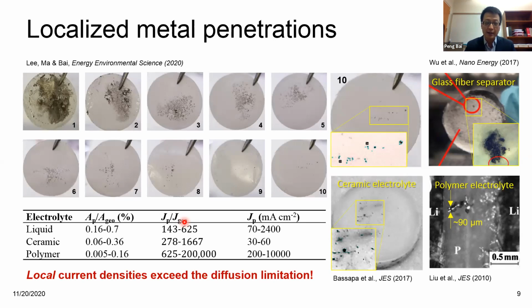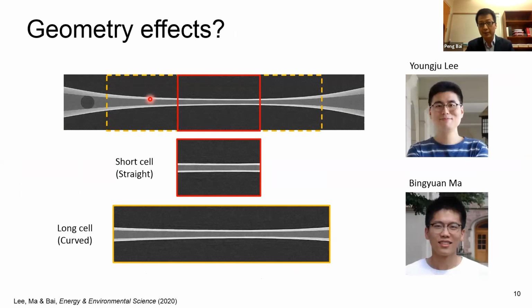But then the second point is that if you pay attention to the collective area, you can see here, the area is reducing. That means along the penetration path, there is a geometric change, right? There is a geometric change. So this is really the first time we're thinking about, maybe it's time to really talk about the geometric effect. And one way to do this is to go back to check our capillary cell to see whether the non-ideal exponent came from the curved structure.